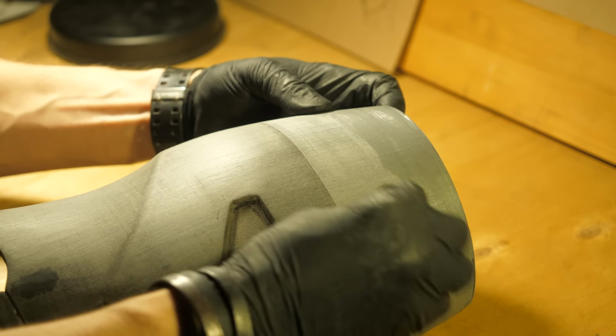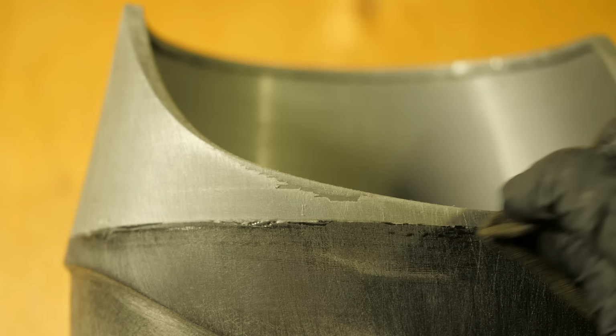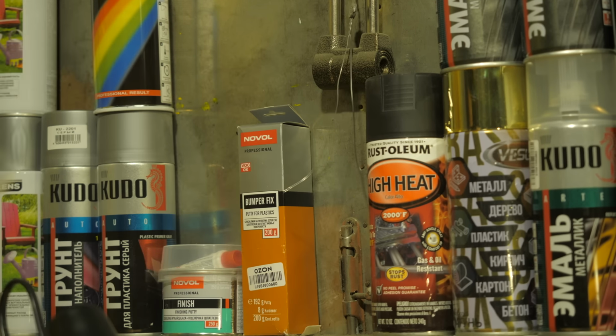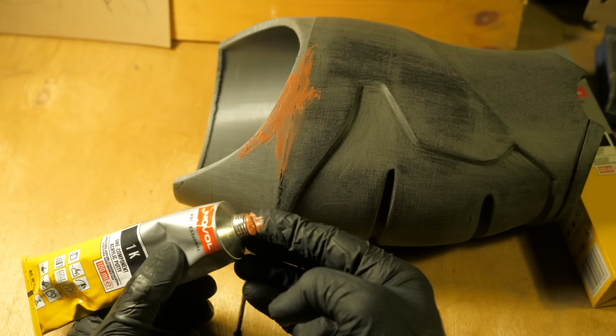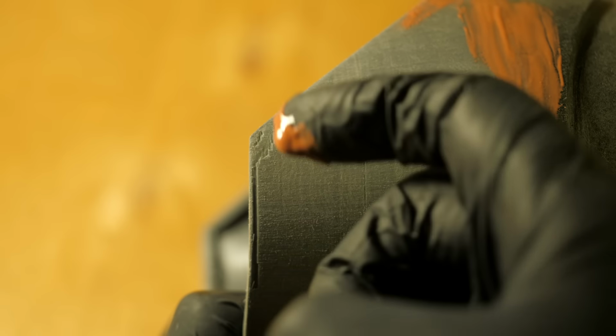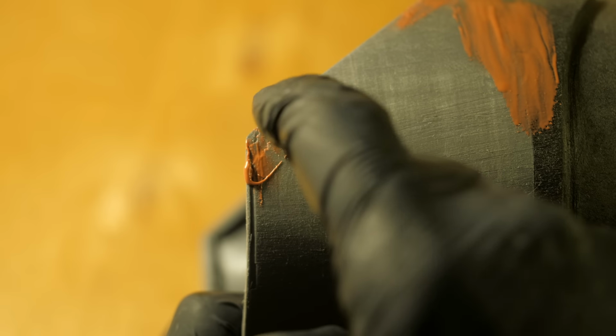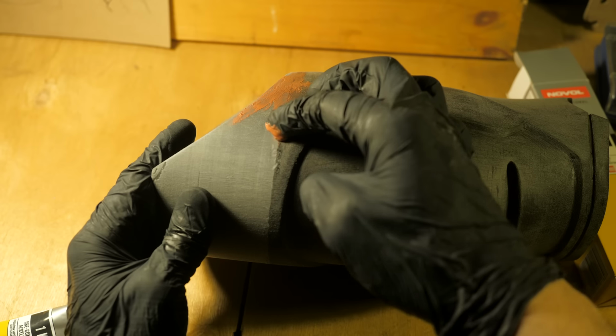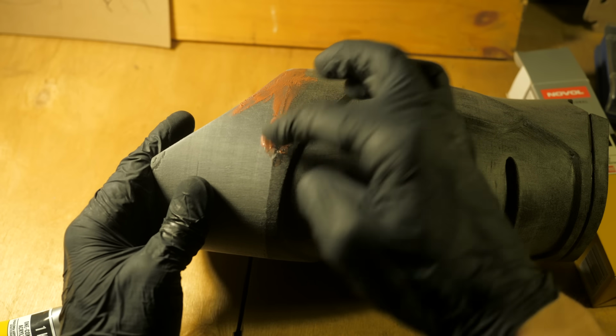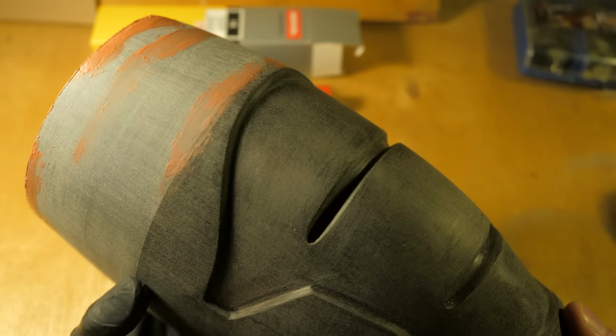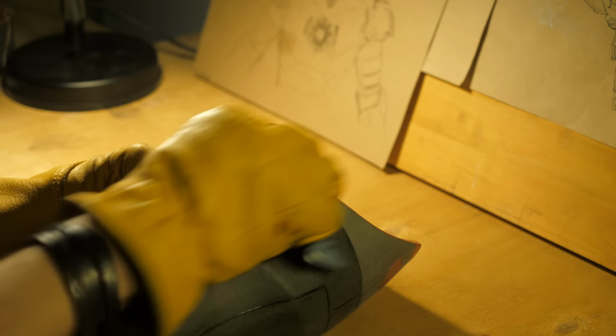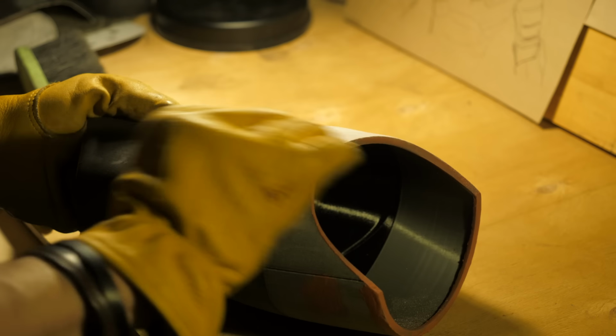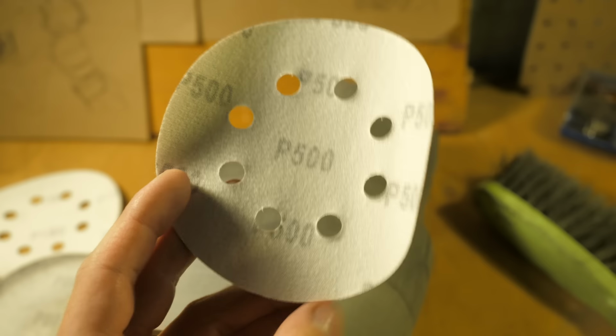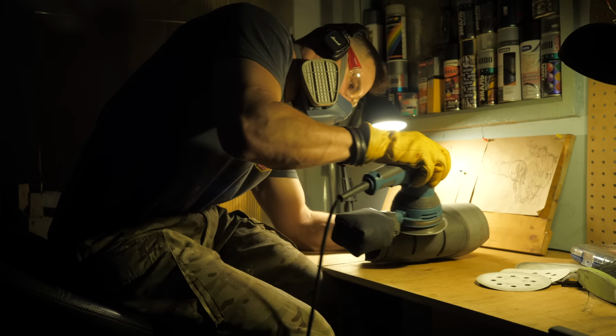Degrease the entire part with a solvent and fill in deep defects with one-component filler for plastic. The more common 2-component filler is not particularly suitable. Maybe I'm a dummy or 35 degrees indoors is too hot for this solvent, but the 2-component filler still cures while I mix it. Remove excess filler and go over the entire area with 500 grit paper.